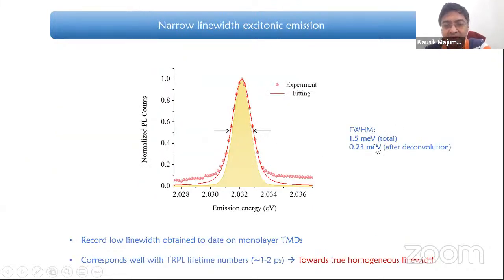The line width that we achieved is about 1.5 millielectron volt, which is a record low number compared to whatever is reported to date in this literature. Please note that in that 1.5 millielectron volt, our laser itself was 1.2 meV because it was passed through a monochromator. If we deconvolute that, the actual line width is 0.23 millielectron volt, which matches well with the reported 1 to 2 picosecond numbers for the lifetime. So we are really going towards the true homogeneous line width in this system.